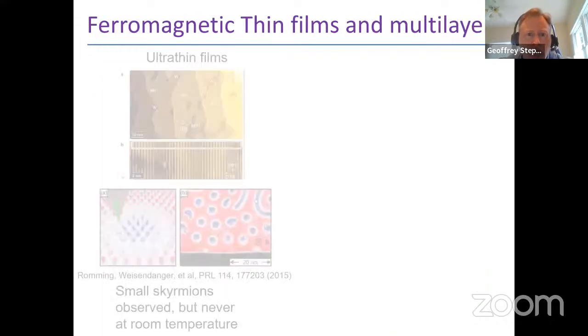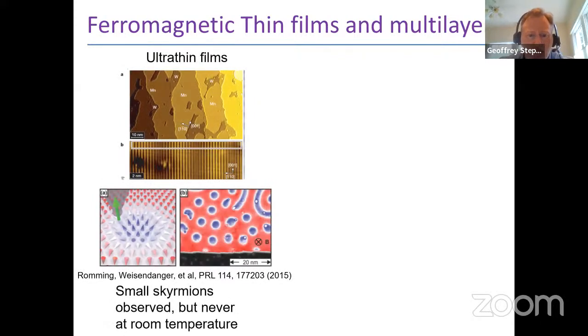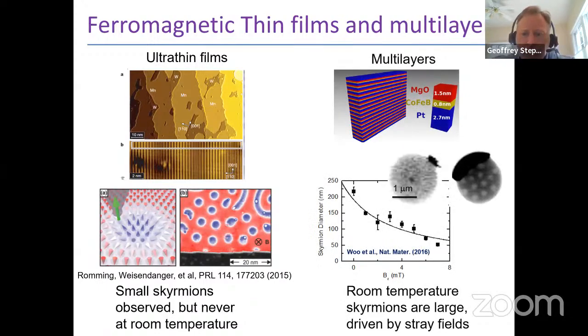Now, one of the problems in these kinds of structures is that much of the excitement at the beginning of work in the field on magnetic skyrmions was the desire or the possibility to have extremely small textures. So textures down to atomic scale, as I mentioned before, had been seen in monolayer or bilayer films on single crystalline substrates. But in multilayer stacks, magnetic skyrmions really across the board are typically very large, usually 100 nanometers or larger, and seldom smaller than about 50 nanometers.